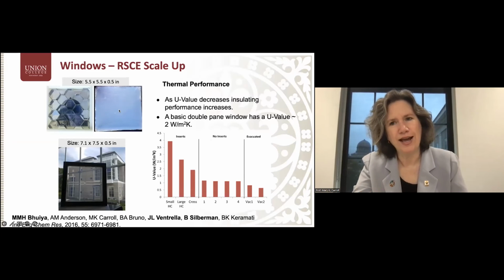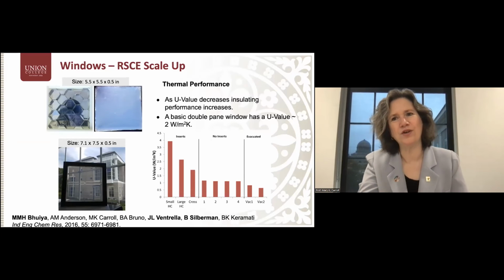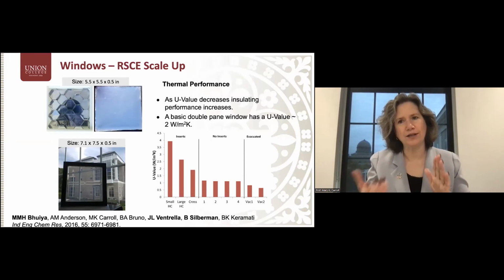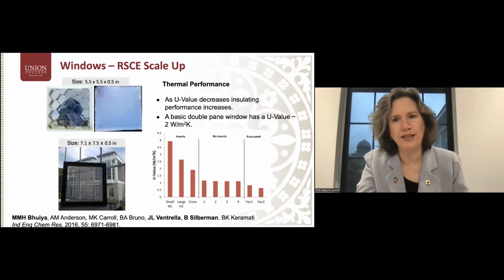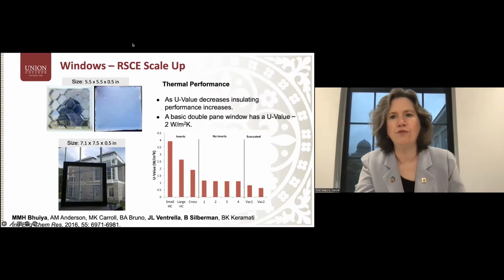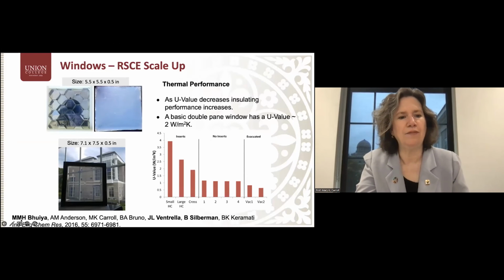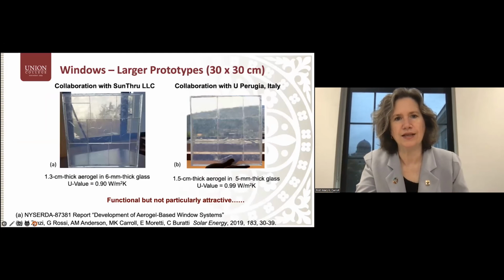And if we then pull a vacuum, as you may know that some window products, double pane products, pull a vacuum in between the panes to increase the insulating. If we do that, the insulating properties improve even farther. And so this was very encouraging, and we are working on scaling this up further.